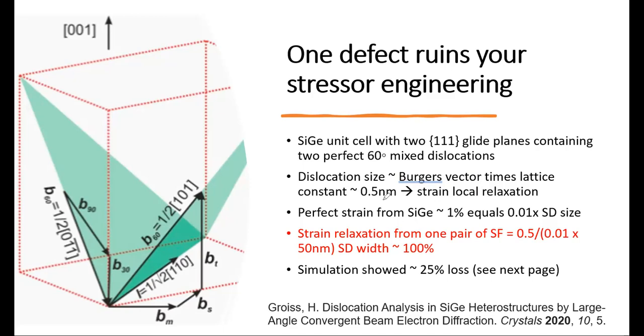Right? 5 angstrom is a nominal value, and that means that's an empty space. And then what does that strain correspond to? See, SiGe, we're talking about 1%. It's difficult to form a 2% strain. So 1% is what? 1% is 0.01 times your source drain size, right? And I use 50 nanometer, so 1% of 50 nanometer is 0.5 nanometer, which is 5 angstrom. And then you have 0.5 nanometer of empty space.